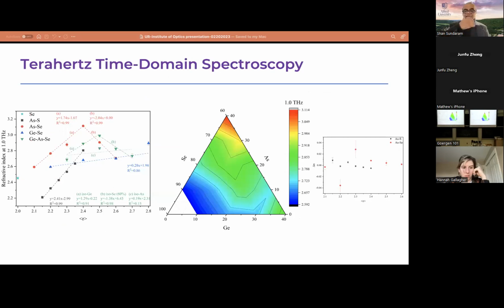What we did, we took the data set and we wanted to map out how the 1 terahertz refractive index changes in this ternary composition diagram. You can see by looking at this diagram by color codes how the terahertz refractive index can be mapped over this composition.